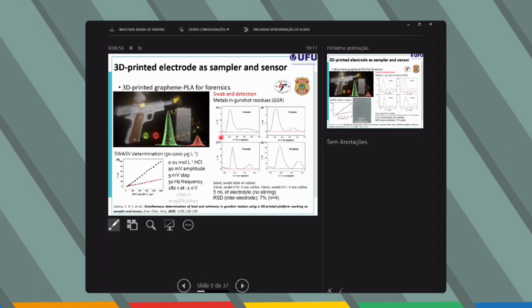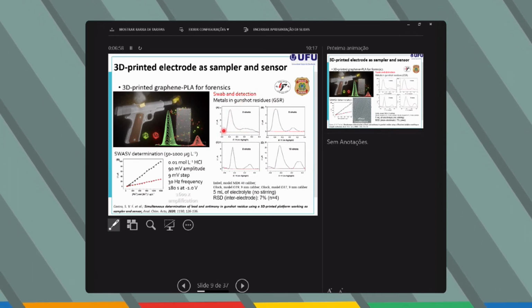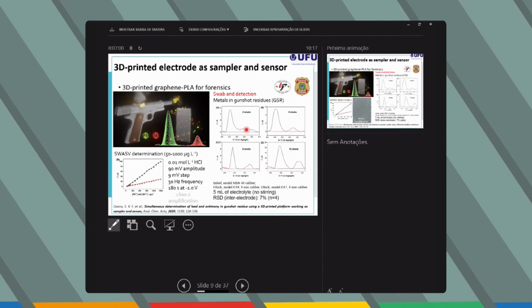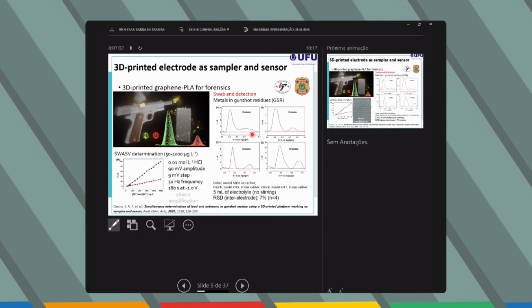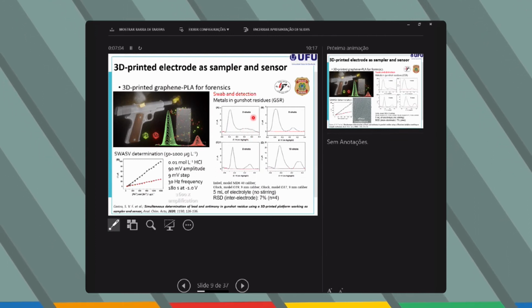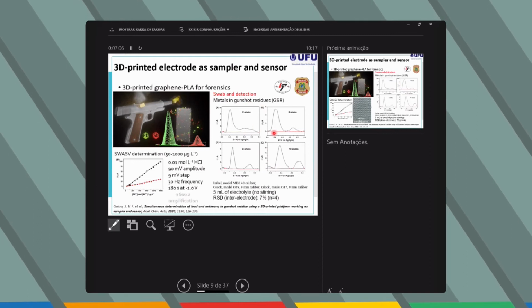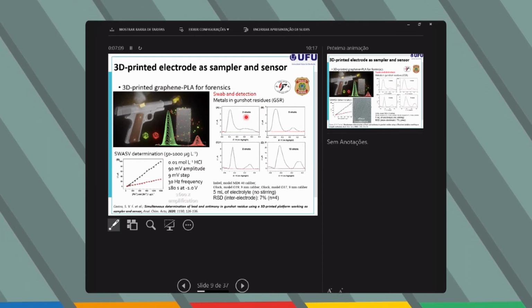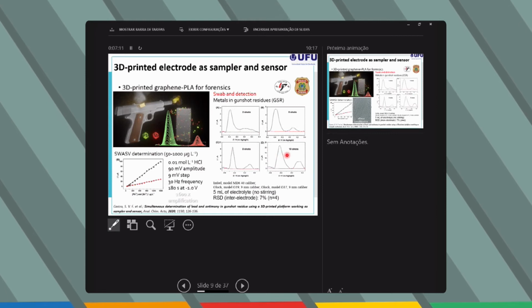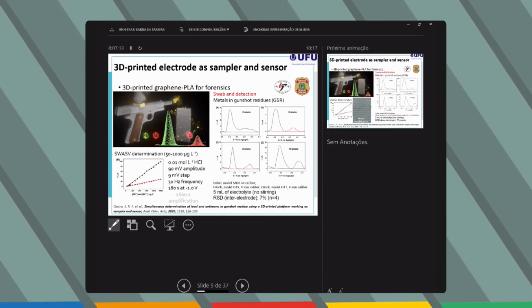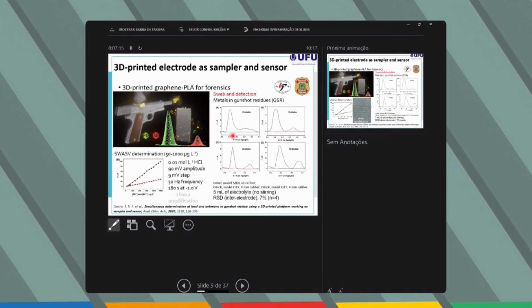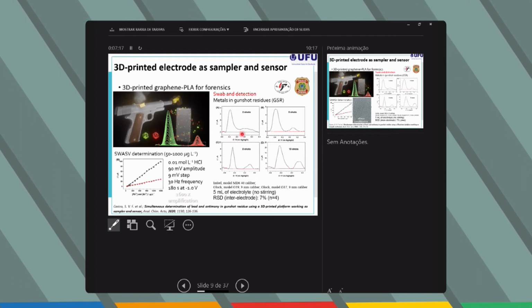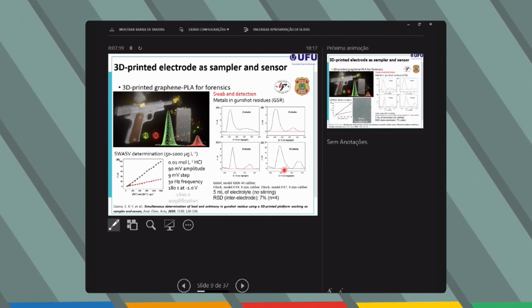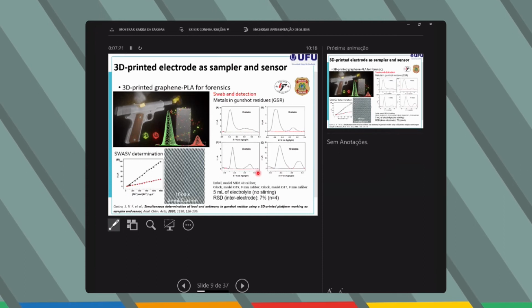In this picture, I show you some voltammograms for the detection of lead and antimony, which are typical metallic contaminants in these gunshot residues. After 2, 5, 8, and 10 shots, this material is swiped over the hands of the shooter, and it's possible to see how the current increased as the number of shots increased.